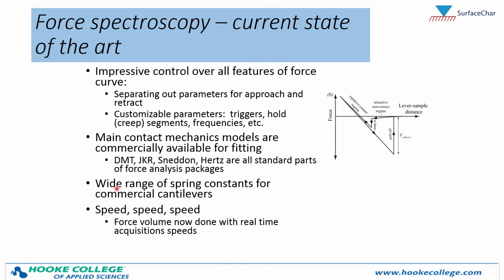We also have a very wide range of spring constants commercially available, which is important, especially as I had mentioned before, you need to match the spring constant of the cantilever to the contact stiffness of your material. So for a wide range of materials, and everything from biological samples in the kilopascals to some stiffer materials in the gigapascal range, all those would require different cantilevers to do these measurements, and we have quite a range available to us now. And finally, speed.